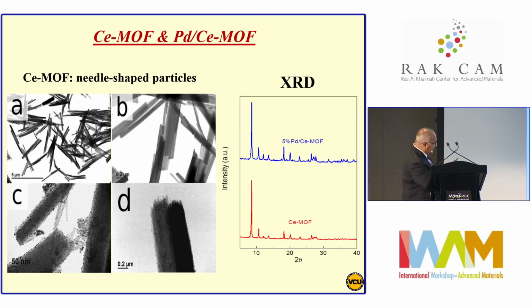So this is first the MOF that was synthesized, the cerium MOF. It forms needle structures, and you can load palladium nanoparticles, that's the catalyst, on this MOF in many ways. And of course, the XRD shows no changes from incorporation of palladium on this MOF, indicating that there are no changes in the structure taking place.